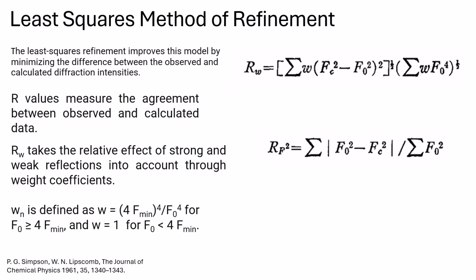Lipscomb used the least squares method as a mathematical refinement tool to improve the proposed crystal structure by minimizing the difference between observed and calculated diffraction data. Specifically, it adjusts atomic positions and thermal parameters to minimize the residue. As you can see here, two equations have been proposed representing two different approaches. In the first equation, there are weight coefficients for different reflections, the strong and weak ones. Intensities do matter here. And in the second equation, the weight coefficient disappears.